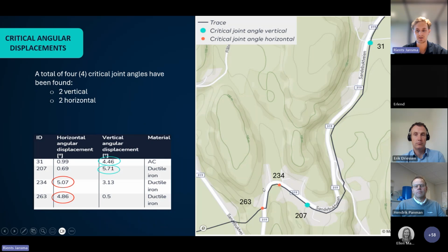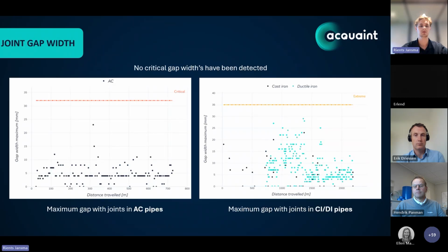So here you can see it's the same map with the numbers, and here you can see the vertical angular displacement. It's critical at 4.46 for AC, 5.71 degrees at ductile iron, 5.07 and 4.86 at the other spots, as you can see here on the right side. Okay, here we see 2 graphs. On the left side, it's the maximum gap width in millimeters, and at the downside, it's the distance traveled in meters. So the left graph is for the asbestos cement. Here you can see both norms, and none of the points is above the norm, so no critical gap widths have been detected. The same accounts for the ductile iron and the cast iron, so no critical gap widths have been detected there as well.